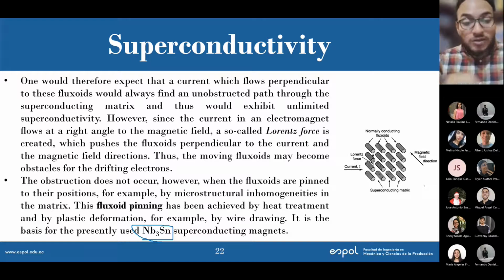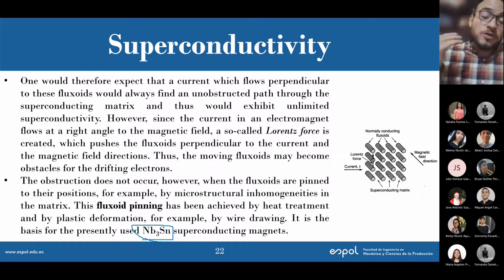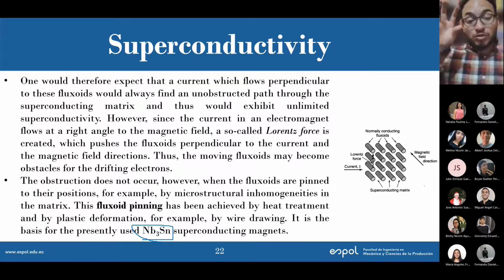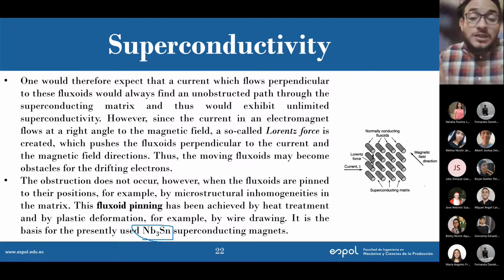Even though you can do this heat treatment or plastic deformation, remember that the higher the temperature, the more mobile the atoms are, right? So you will induce lattice vibrations. Once you are at those temperatures, you will already have lattice vibrations. So even though you can do a heat treatment and plastic deformation to try to pin your fluxoids, because of the lattice vibrations, you will still have some movement. My fluxoids will move because of these thermally induced vibrations, and therefore electrons will collide with those fluxoids. As a result, I won't have that effect of fluxoid pinning. I still have motion of my fluxoids, and they are not pinned. Any questions, guys?